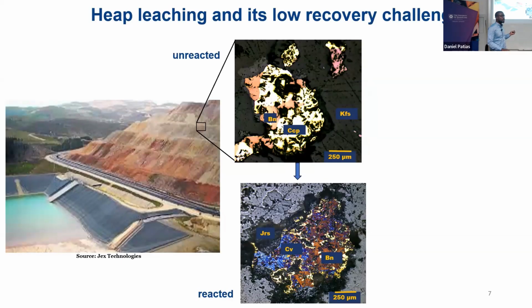So there's a secondary copper sulfide mineral, covellite. And where the chalcopyrite was initially, it's being transformed more to a deep brown material, bornite in this case. Realistically, the formation of these phases results in less copper dissolution.